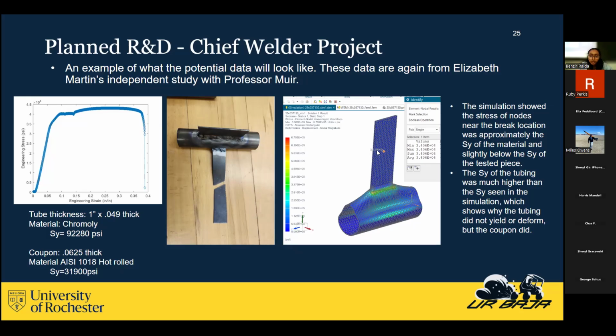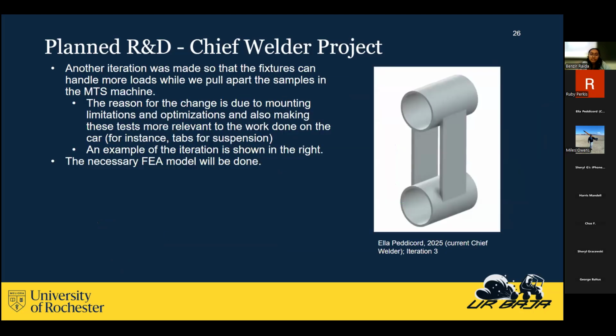stress nodes near the break location was approximately the yield stress of the material. So approximately is around the same as 1018s and slightly below the yield stress of the tested piece. And the yield stress of the tubing was much higher than the yield stress seen in the simulations, which shows why the tubing did not yield or deform, but the coupon, which is the tab itself, did. This is again to reiterate the idea of what our potential data would look like.